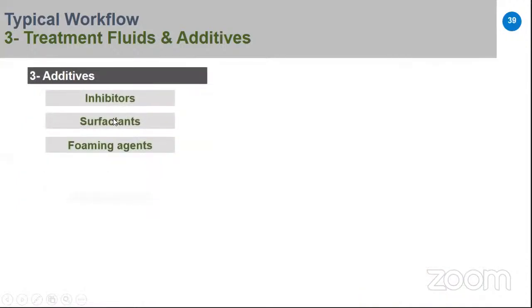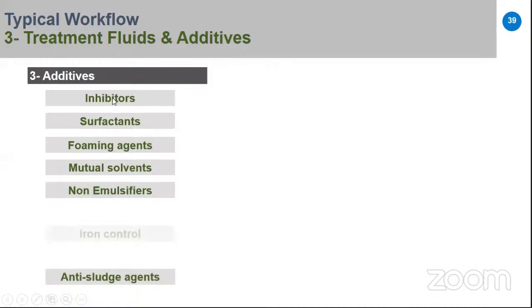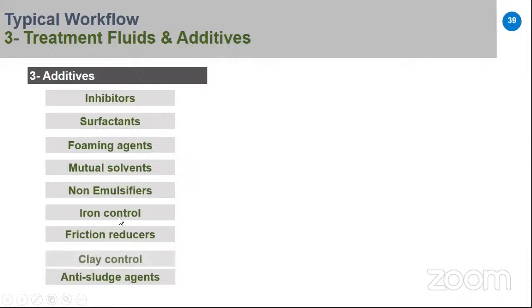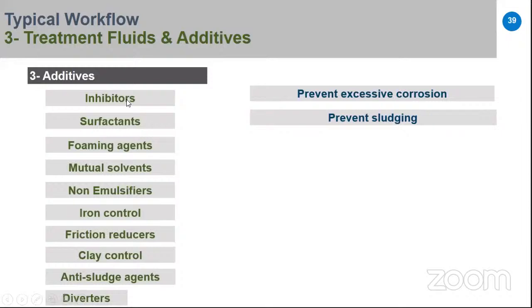Also, we have a lot of additives in our stimulation job. This includes inhibitor, surfactant, foaming agent, mutual solvent, iron control agent, friction reducer, clay control, anti-sludge agent, and diverters. Each one of these is in a catalog, or you can ask the supplier directly. You should know why you use an inhibitor. If you use HCl, you should use an inhibitor to reduce the corrosion rate. For each one, you have to know the functionality of the additive.